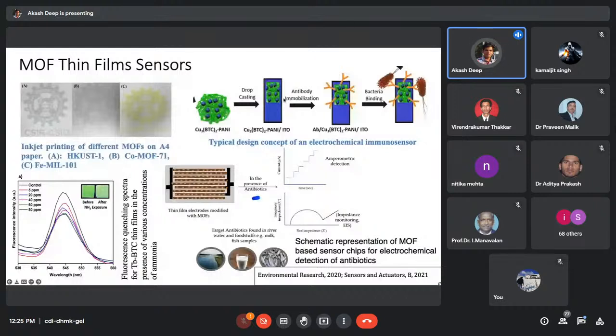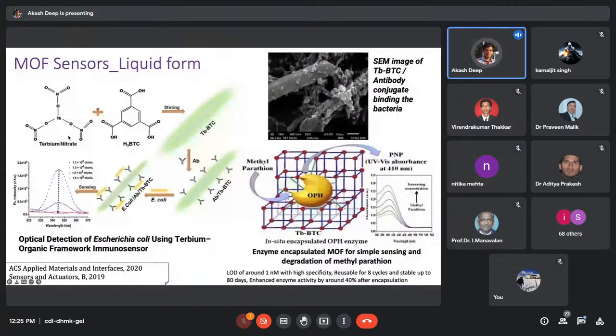Then this is an example of how liquid-based, solution form-based materials can be used as sensors. One of the examples is shown here. In this case, one MOF was synthesized by mixing terbium nitrate and H3BTC, simply by stirring. Then it led to the formation of this complex Tb-BTC. It's a nanorod type of complex and it shows green fluorescence. We then modify it with antibodies which are specific to E. coli bacteria. And when the E. coli bacteria comes in contact with, or is mixed with, this solution of Tb-BTC MOF, it leads to the quenching of the fluorescence. Here you can see that different concentrations of the bacteria cause different extents of quenching in the fluorescence signal.